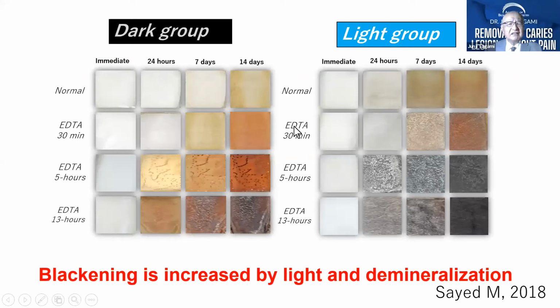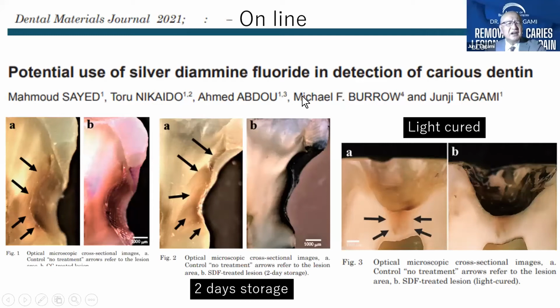Interestingly, if you apply the light onto this solution, even without the caries region, the color of the SDF becomes very dark. By the light curing, the color is changed to black. Of course, if we apply this solution onto the demineralized dentin, the discoloration, the blackening is much stronger. And we tried to evaluate this SDF solution as a potential for caries detection.